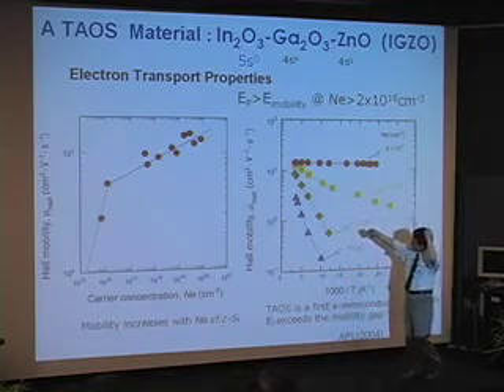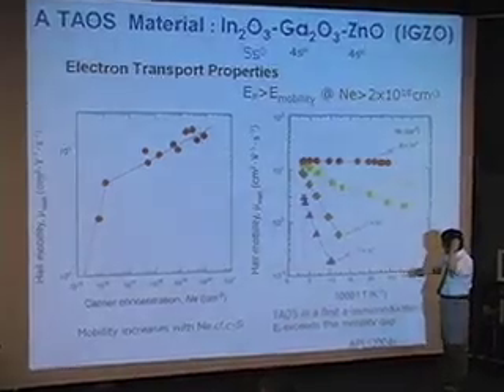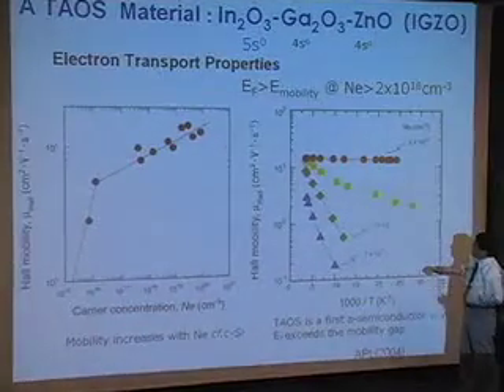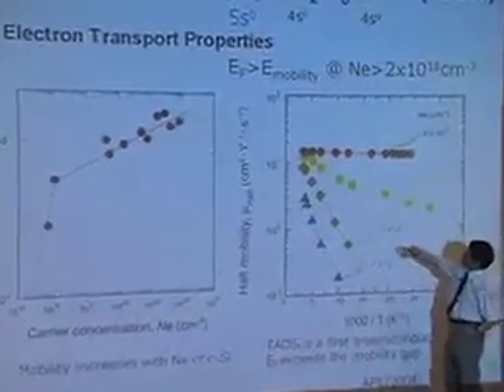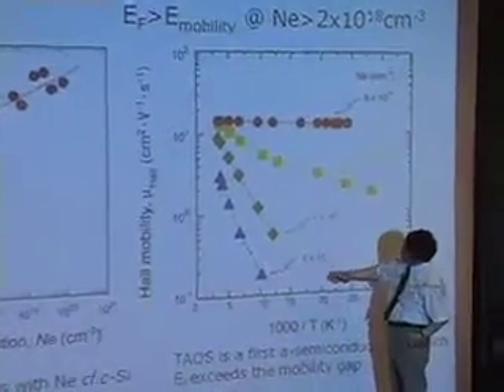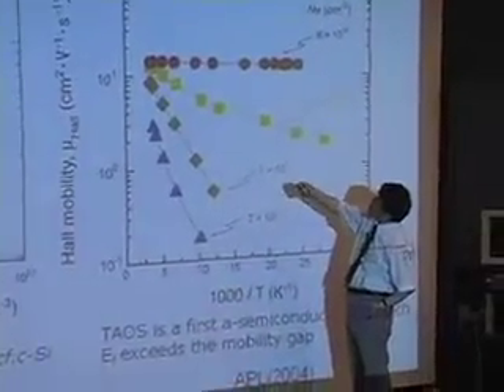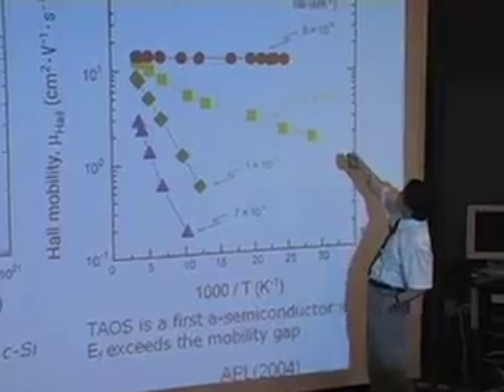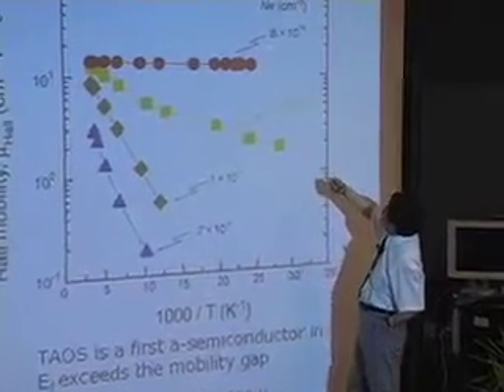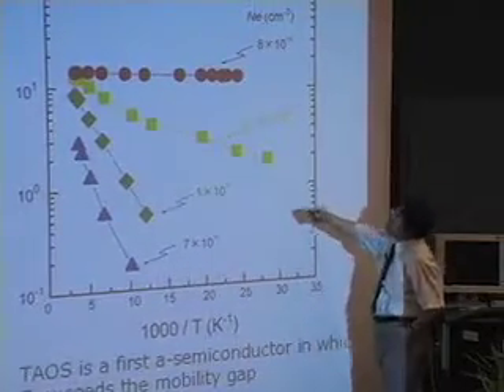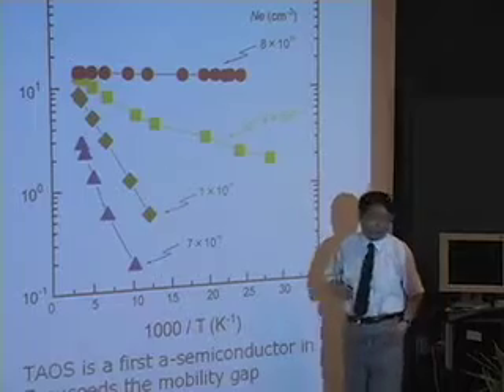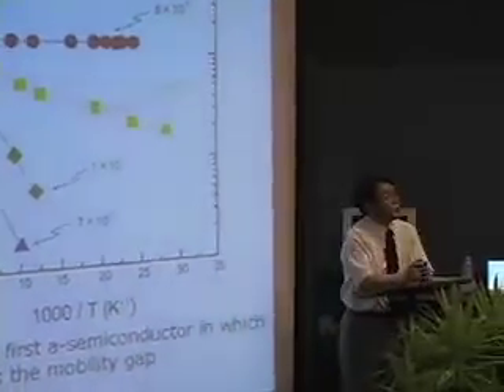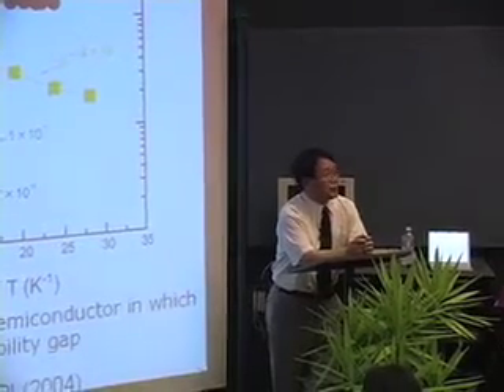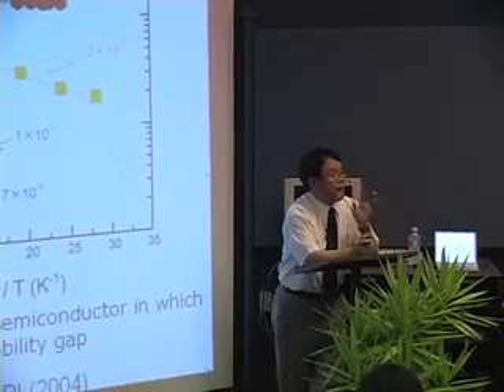This is the Hall mobility as a function of temperature. When the carrier concentration is low, it shows activated-type behavior. When the carrier concentration exceeds 2 times 10 to the 18th, it's almost constant. This is the first material that exhibits metallic conduction, meaning the Fermi level exceeds the mobility gap.